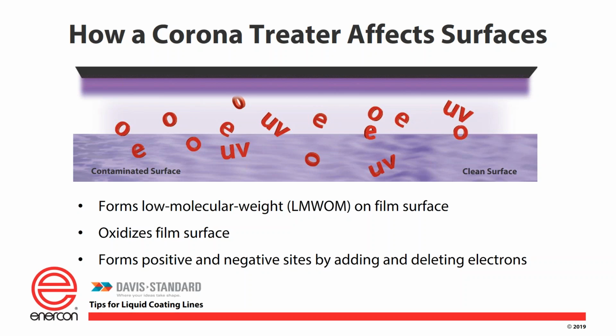So really what happens here is we have all these low molecular weight materials on the surface of the material, and the corona treater takes that material, we oxidize that, we put oxygen into the surface, we form these positive and negative sites by adding and deleting electrons in the corona field. And that cleans the surface, of course, getting rid of some of those migratory agents that are on there. And when we do all that, we end up now with a surface that goes from a non-polar surface to a polar surface, one that was kind of dirty and not suitable for silicone coating in this case, but now is. And the corona treater is doing its job. It's cleaning and functionalizing that surface so that the coating process does what it's supposed to do.